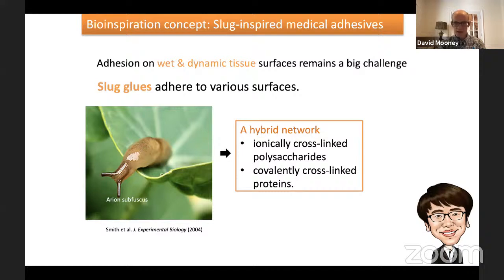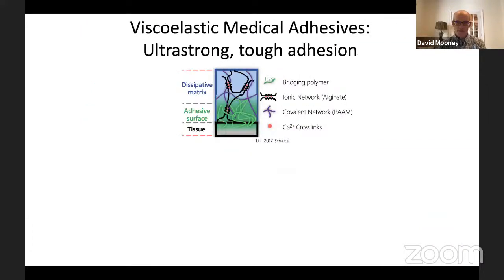When one looked at the composition of this mucus, it was a hybrid network comprised of ionically cross-linked polysaccharides and covalently cross-linked proteins. And Jianyu realized that this sure looked a lot like these gels that Xuanhe had been making that were able to dissipate so much energy. And so he proposed that one could create new types of viscoelastic medical adhesives that would provide ultra-strong adhesion by combining these, what we call tough gels, these dissipative matrices, with an interfacial material that could form strong bonds between the underlying tissue and the gel.